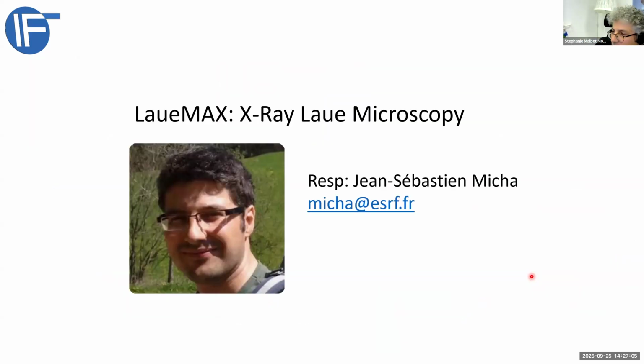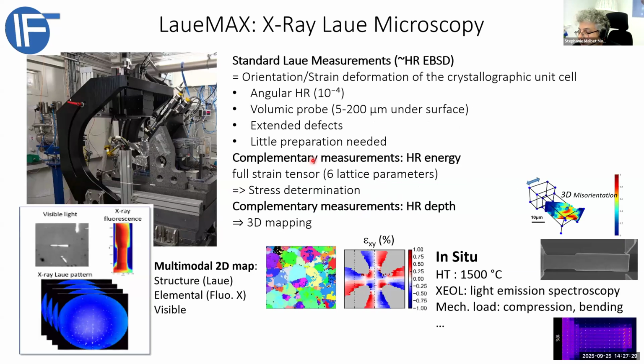And the last instrument, and I'm more involved in this instrument, is the Laue-MAX instrument, which is able to do X-ray Laue microscopy. So this is an imaging technique, and X-ray Laue is scattering. So this is a combination of diffraction and imaging. This technique is similar to EBSD, if you know that. It is a technique to measure the orientation on your surface.